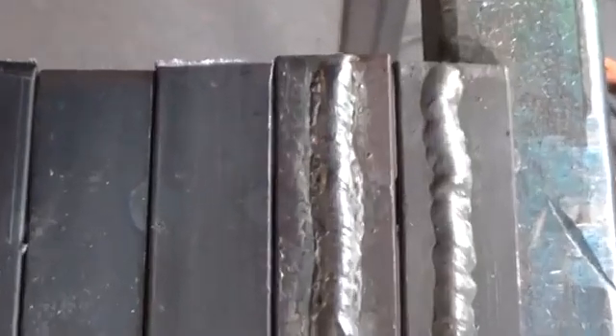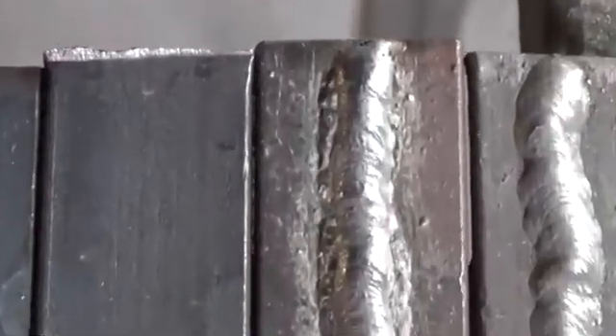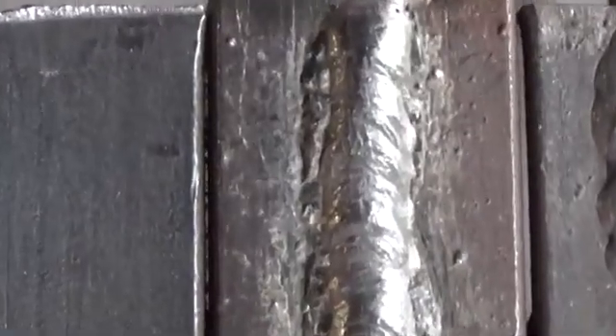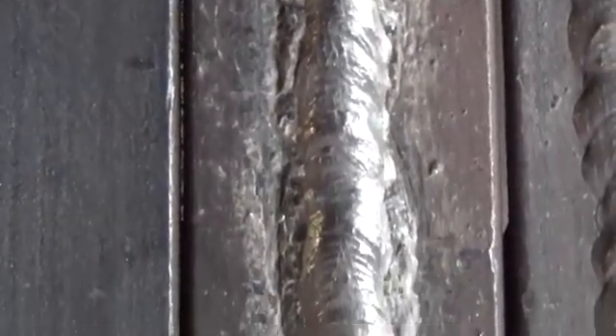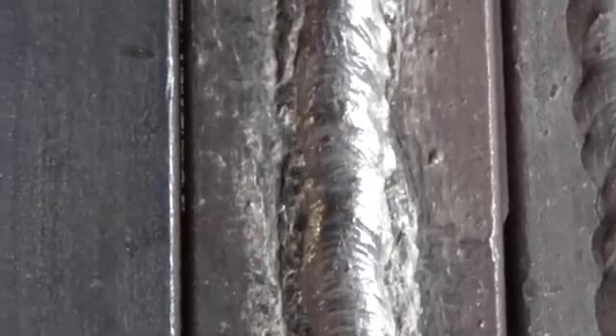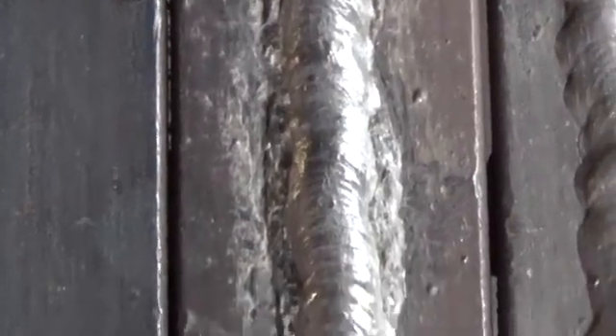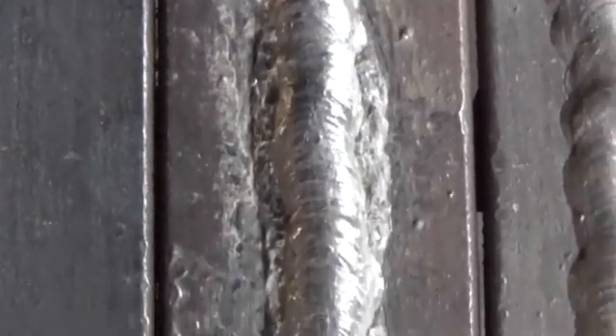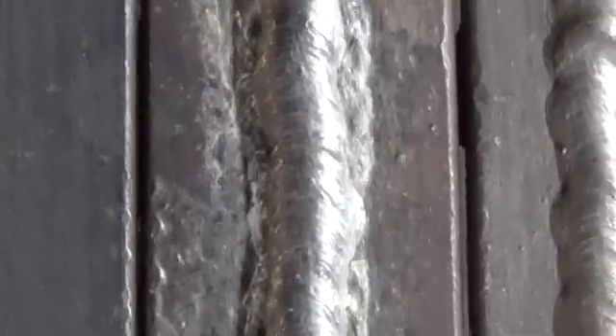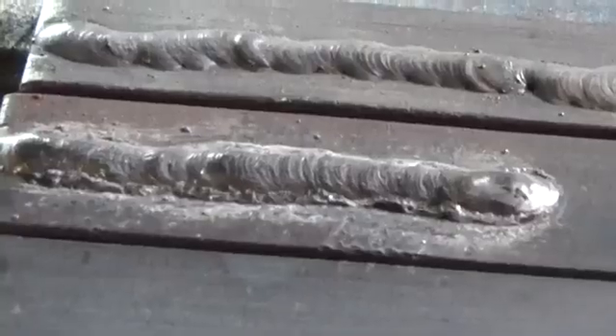Here the slag is visible on the edge of the weld. As you can see, the shape of the weld in this case is similar to the seam welded by rutile electrodes. It is too narrow and high. Current is clearly not enough. The next seam, basic electrode positive, current is 73. In this case I would say that this is the optimum welding current.